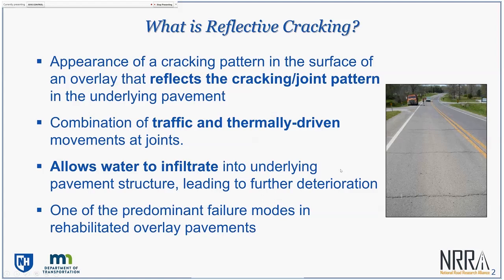And also they provide another pathway for water to infiltrate into your pavement structure that continuously degrades your ride quality, because now you have potential for ice wedges to form underneath these cracks, leading to a tenting type of effect. And also free edges in asphalt are not good because unlike concrete, it's not able to support that free edge, and you would have a continuous degradation that would really lead to very high roughness in your pavement.